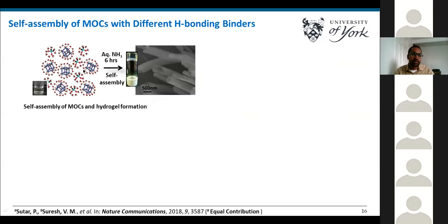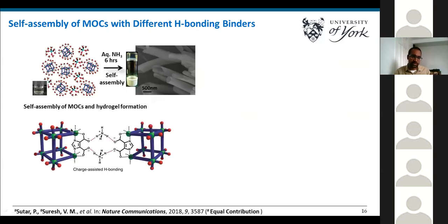When we add aqueous ammonia to the MOC solution, within 6 hours, the MOC gets assembled and forms a hydrogel, which is quite stable over a long period of time. And the MOC gel, when it is dried, we see formation of tubular nanostructures, as we see from scanning electron microscopy. So the possible assembly is MOCs bridged by ammonia instead of the dimethyl ammonium cation in the previous structure. So now the ammonia connects the metal organic cages through charge-assisted hydrogen bonding and extends the assembly in a three-dimensional way, where a large amount of water gets trapped and results in the formation of hydrogel.